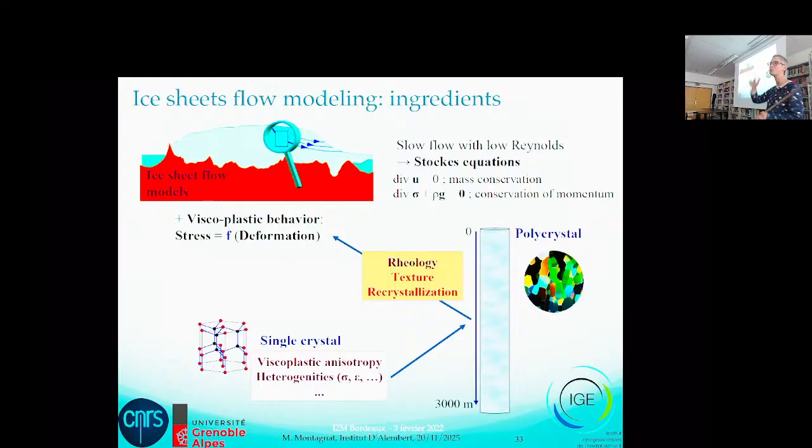On olivine, of course, we need much more pressure, much higher temperature. And at the same time, ice was limited for doing in situ experiments with EBSD, so in a scanning electron microscope. So we are using magnesium right now. And so we are making some in situ experiments on a magnesium alloy to follow the dynamic recrystallization mechanisms. So it's a little less anisotropic than ice, but we can make some parallels.